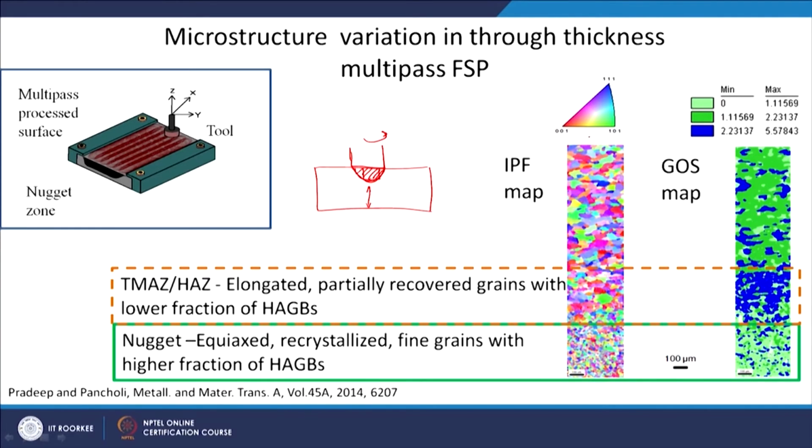These are very long scans. You can see that the scale is 100 micron. So, in this direction the thickness must be around 700 to 800 micron or so, up to maybe 1 mm length. If you see up to where the pin is going, the grain size is refined.